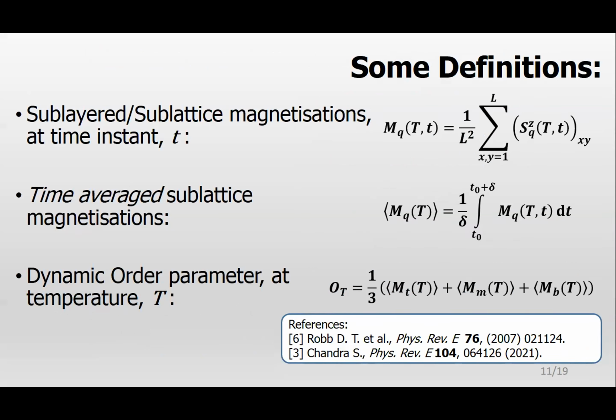We can clearly distinguish that the first one is for sublattice magnetizations at any time instant small t, where the sum is over all spin orientations on a particular plane. Here small q stands for the top, mid and bottom layers as and when needed. The second one is how the time average is calculated, with T naught and delta being same as before. Now comes the important one, the dynamic order parameter. It is basically the total magnetization time averaged of sublayered magnetizations of the top, mid and bottom layers.